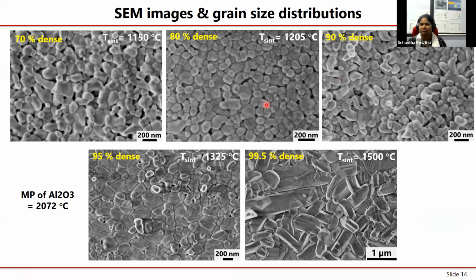So sintering was done at temperatures based on the melting point. We know that aluminum oxide has a melting point of 2072 degrees Celsius, and usually when we pick sintering temperatures, we pick more than 0.4 times the melting point, in the Kelvin scale. I optimized and found that for different temperatures, I get different densities. At 1150 degrees Celsius, the sample has around 70% density, which means 30% is porosity. At 1205, it's 80%. At 1250, it's 90%.